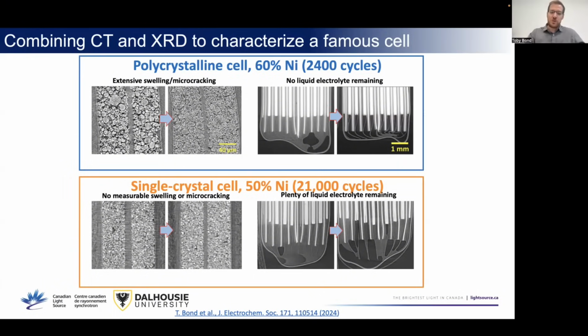So if I was going to look at these cells and evaluate them for use in grid energy storage as a second life application, even though these cells have about the same level of capacity loss, I would much rather be using the single crystal cell because it's much healthier. There's lots of electrolyte left. There's no evidence of this microcracking. It should continue to degrade in a very predictable way.